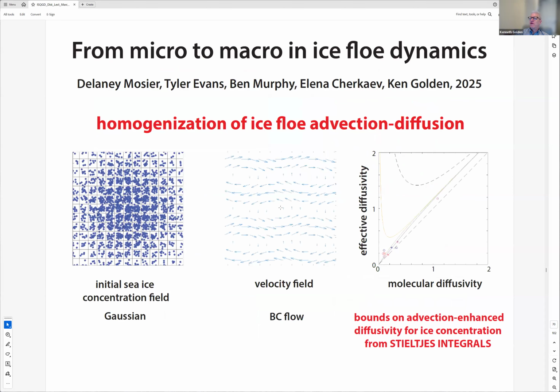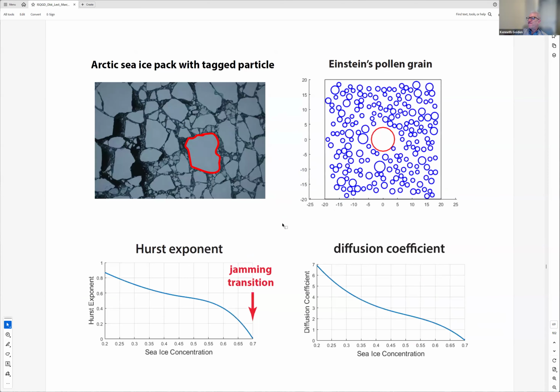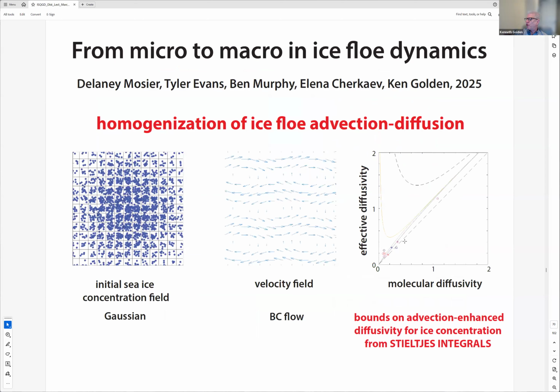This is showing some of the advection. We can actually then use our Stieltjes representations to calculate the effective diffusion coefficient, and we get beautiful correspondence of those rigorous bounds, these Stieltjes bounds, with our calculations of the large-scale advection enhanced diffusion coefficient, I should say.